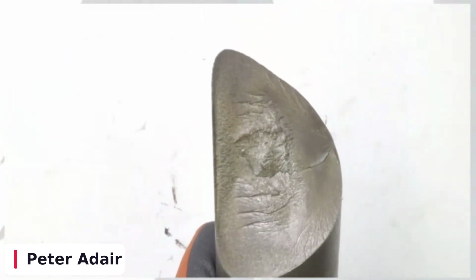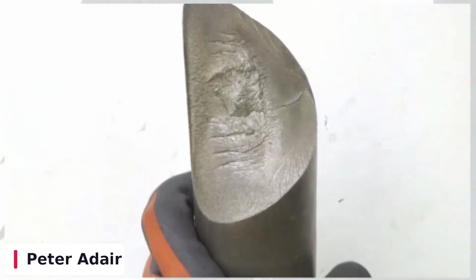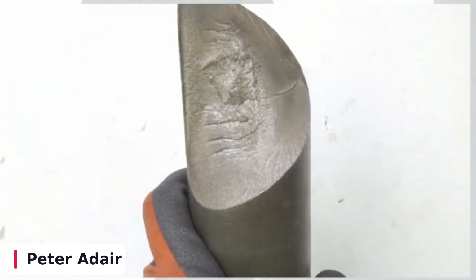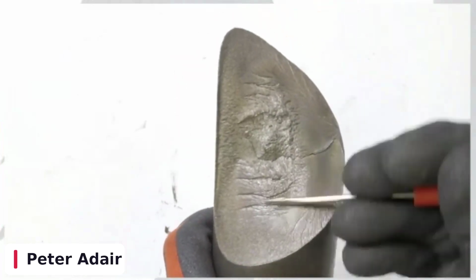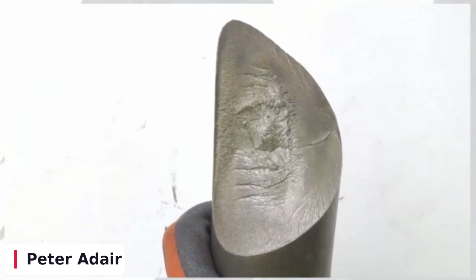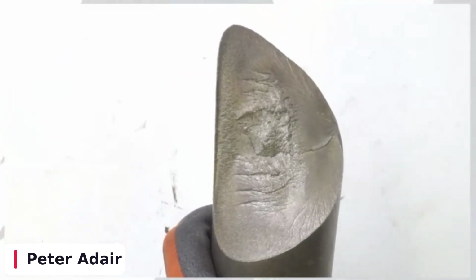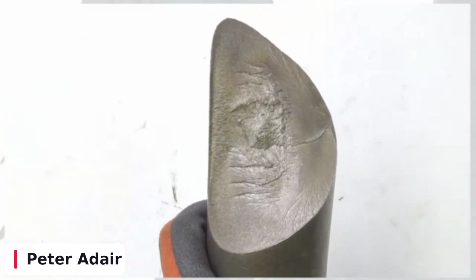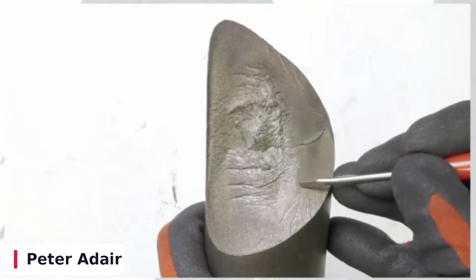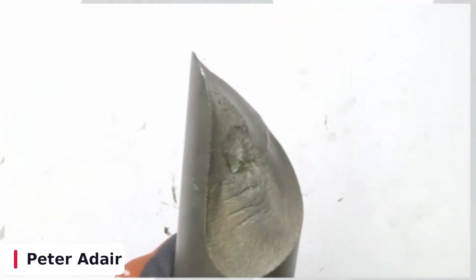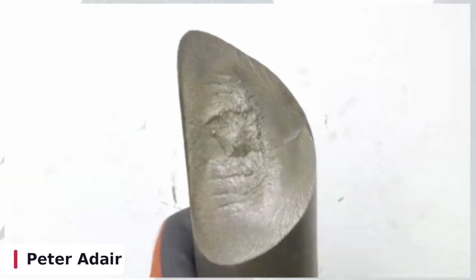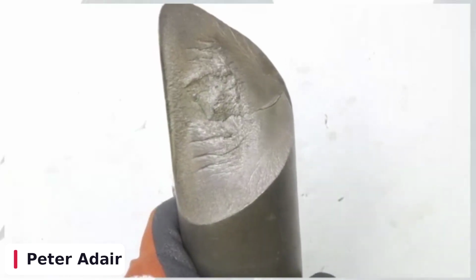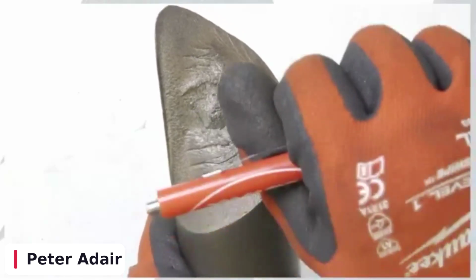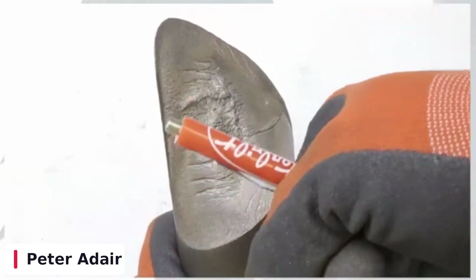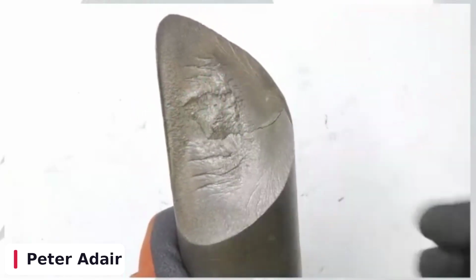Now, the cool thing about this is called a torsional tensile fracture. Tensile because it's at a 45-degree angle. Now, we have a torsional shear fracture, which we'll look at next. But in this instance, torsional tensile. So tensile is always going to be your 45-degree break. Now, what does the 45-degree break tell you? It tells you it was loaded, meaning it was already twisted and kept twisting as it snapped.